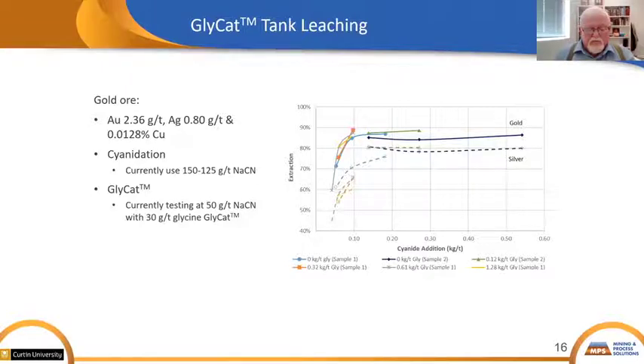The value of the saved cyanide is not much, but the possibility to increase gold recovery in a large milling complex by 2 to 3% is, of course, of great interest. It's even more interesting if the predicted reagent consumption is reduced. And we're doing an intensive series of bottle roll tests on these samples now.